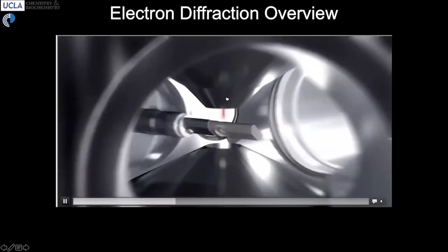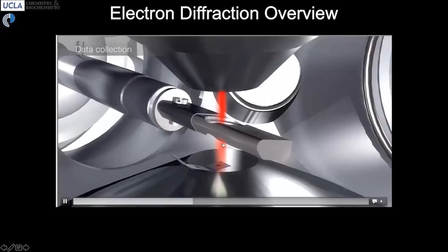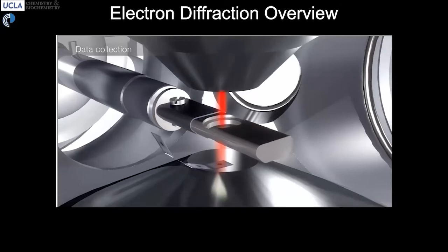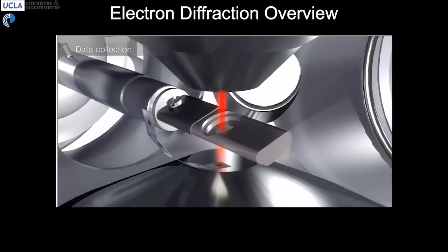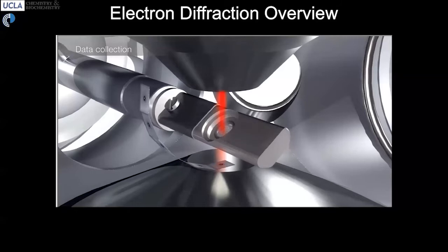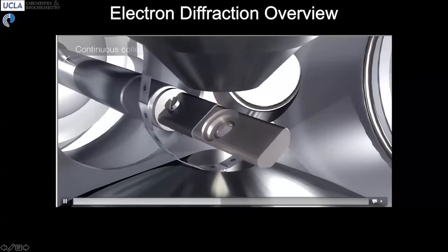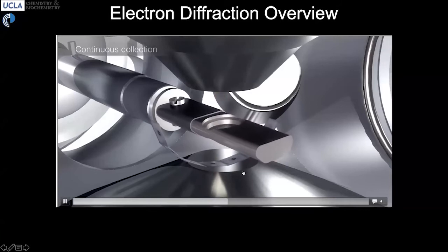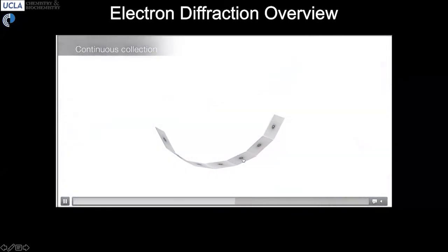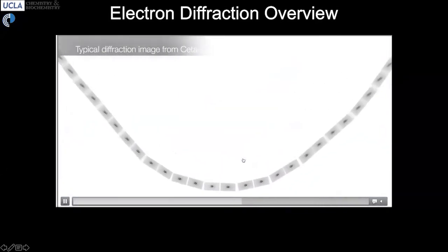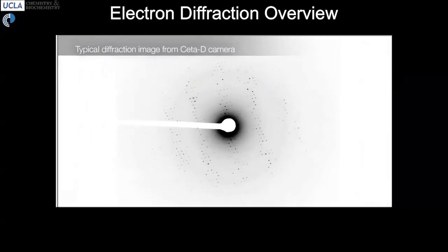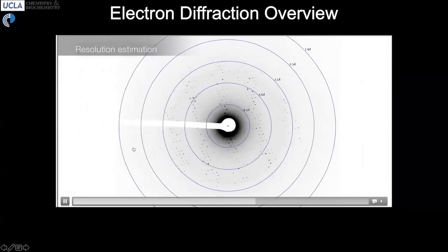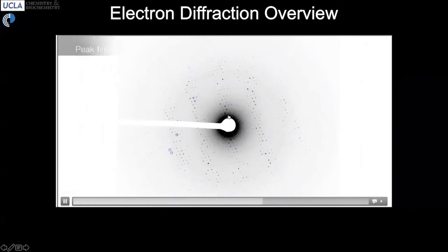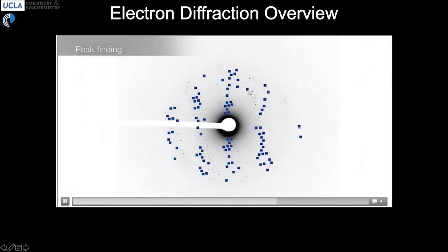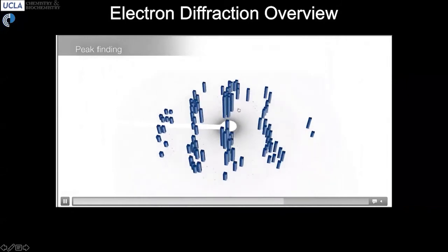The TEM would then illuminate them with an electron beam as you're rotating to capture diffraction at various views or angles from that crystal. Those diffraction patterns would be collected using a detector that's sensitive to high energy electrons. And that detector actually sits farther below the interaction region. This is just simulating what you might see. You might see a diffraction pattern that looks like this, where constructive and destructive interference of electrons with the lattice in your crystal has been measured.